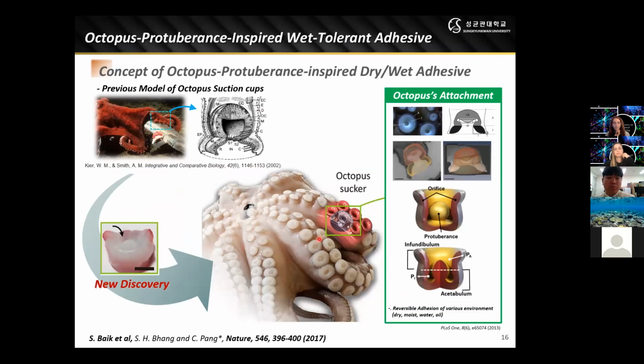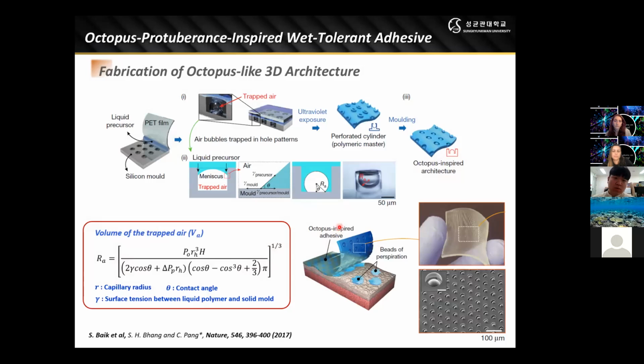Octopus suction cups have special properties in attachment in underwater environments. So we particularly mimic the dome-shaped protuberance in the octopus suckers based on a biological new discovery. Such dome-like structure in suckers is known to interplay with adjacent walls and generate additional secondary chambers for strong wet adhesion. These octopus-like microstructures can be fabricated with an air trapping molding technique and multiple applications. Herein, we can control the trapped air bubble by using an energy balance between the polymer precursor and the surface of the master mold.